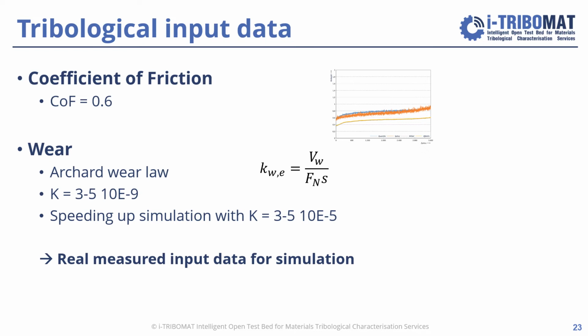But we are also interested in wear, if potentially wear occurs in the time of interest. And for that we use the Archard wear law. The Archard wear coefficient, which is proportional to the wear volume and linked to the normal load and the sliding distance, was found in the experiments to be between 3 and 5 times 10 to the power of -9. In order to speed up the simulation, we increased it to the power of -5. So that enables us to really simulate many cycles in a shorter simulation time.